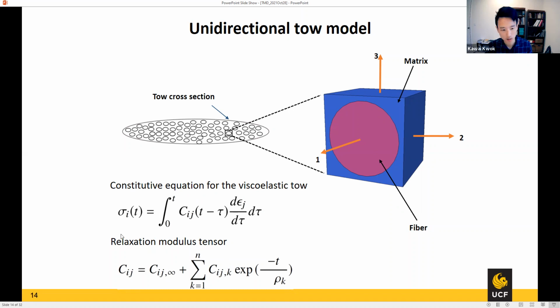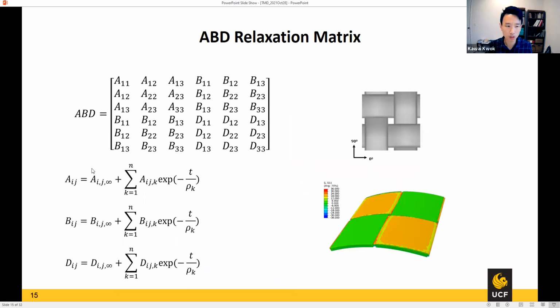So this is just the classical Boltzmann superposition integral for viscoelastic material. You have the strain and stress, and it's an integral equation over time, right? So this is no longer elastic but viscoelastic, and all of these are described by a relaxation modulus tensor. Each of them is going to be a Prony series, which is a series in time described by relaxation times. From the matrix that we characterized experimentally, and the fiber, which is at the moment assumed to be linear elastic, we can compute this general tensor, which is anisotropic, but all of the terms are time dependent. Taking from that, we can go to the next level, because each of these tows in a plane is now described by a time-dependent stiffness matrix C.